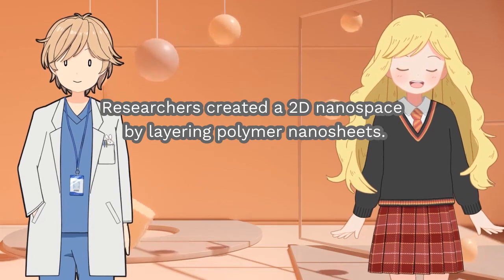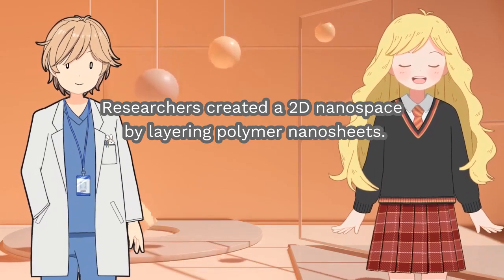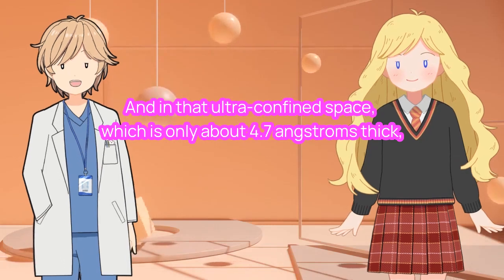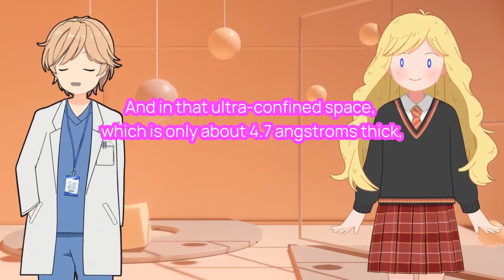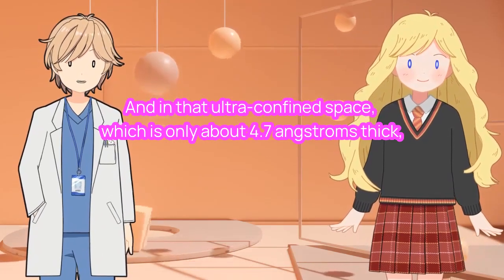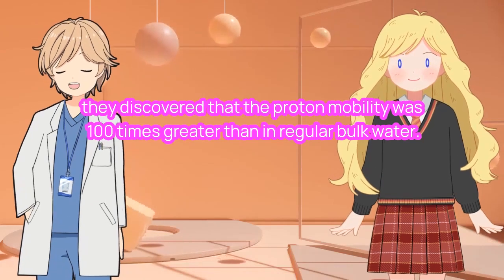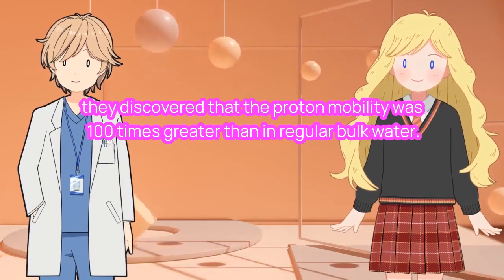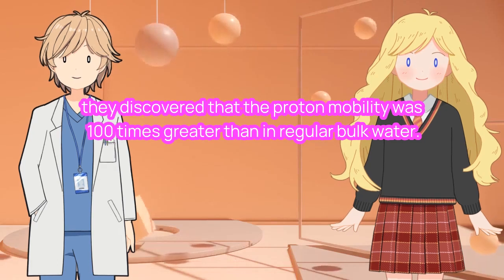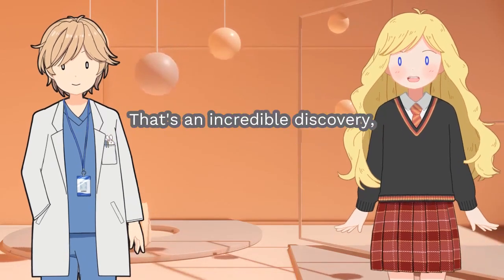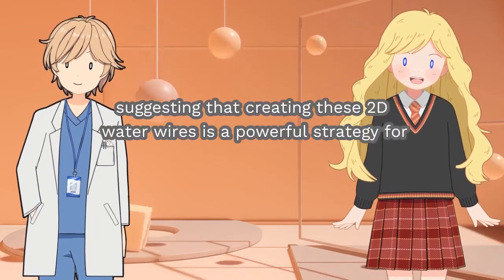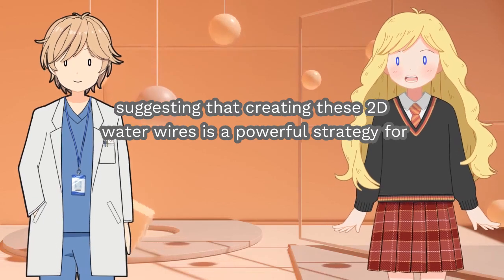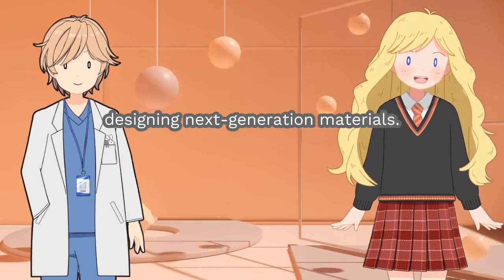Researchers created a 2D nanospace by layering polymer nanosheets. And in that ultra-confined space, which is only about 4.7 angstroms thick, they discovered that the proton mobility was 100 times greater than in regular bulk water. That's an incredible discovery, suggesting that creating these 2D water wires is a powerful strategy for designing next-generation materials.